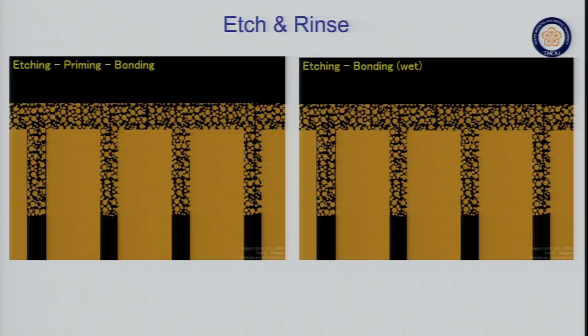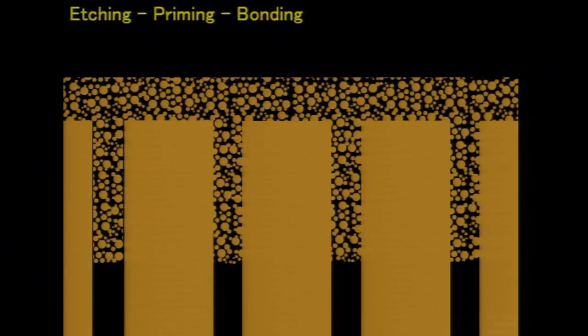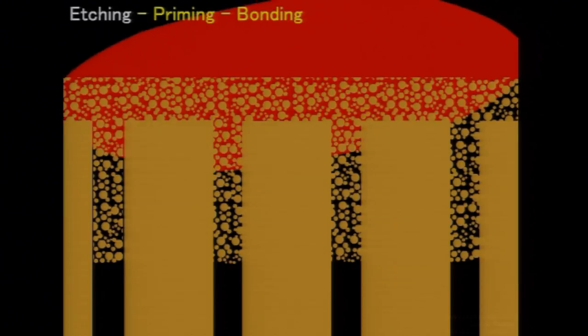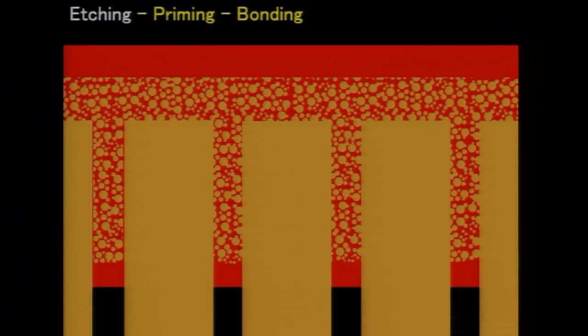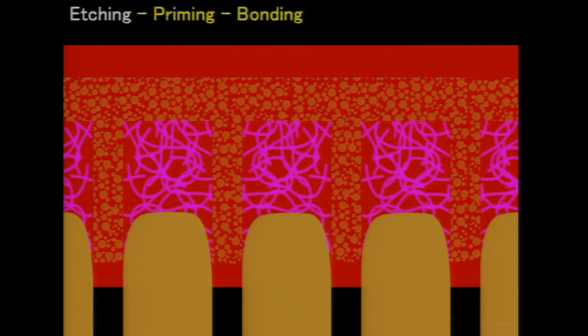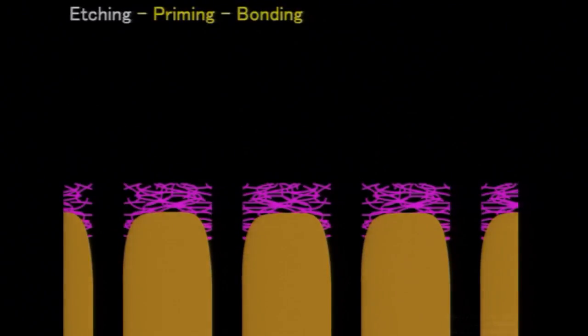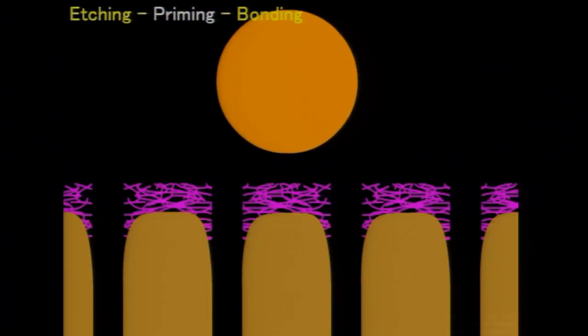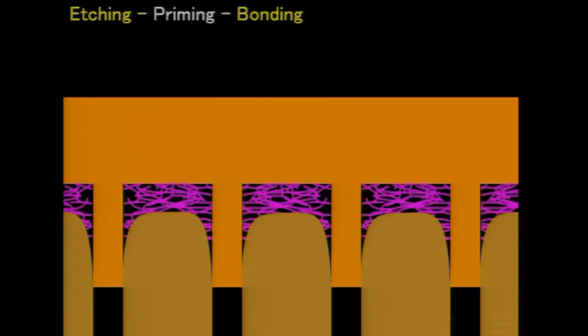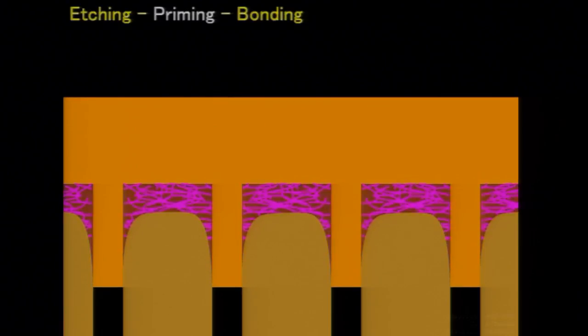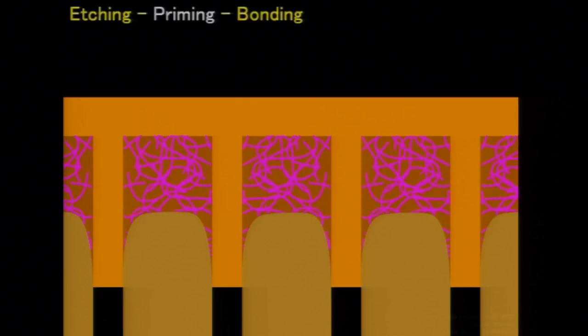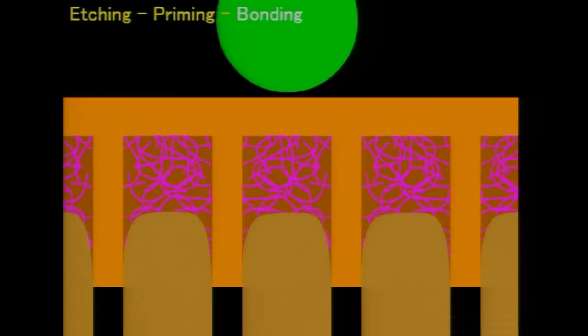Again, I'll show you the animation in the case of the three-step system: etching, priming, bonding. The etching is the same. Phosphoric acid is very strong, and to re-expand the shrunk collagen layers, the primer application was recommended. Of course, it was very effective to re-expand the shrunk collagen layers, and the space among the fibers becomes bigger again, and the bonding resin can penetrate into this layer very well.